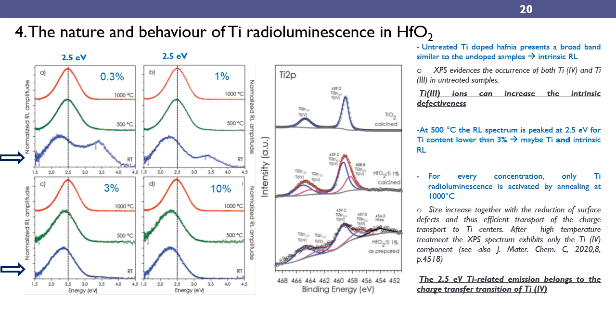This fact is also supported by the XPS data, as they reveal the presence of both titanium 3+ and titanium 4+ in the lattice. Since the presence of a trivalent dopant ion involves a charge compensation in hafnium oxide, defects like vacancies are created, and so, in the smallest nanoparticles, the intrinsic defects are efficient luminescence centers.